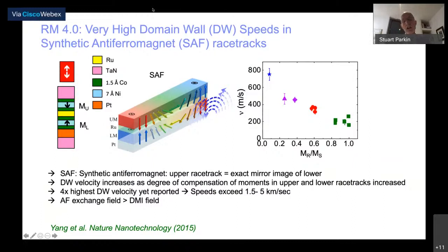And it relies on the oscillatory interlayer coupling through transition metal layers that I discovered in 1989. And in this case, shown in this cartoon, you can see a racetrack which is formed from two racetracks, a lower racetrack and an upper racetrack. They're separated by an ultra-thin layer of ruthenium, approximately 7 angstroms thick. And this causes very strong antiferromagnetic coupling between all the magnetization in the lower racetrack and the upper racetrack. And by designing these upper and lower racetracks to have the same magnetic moment, this means that in the racetrack, there is no net magnetization and therefore no dipole fields. This means there's no interaction.